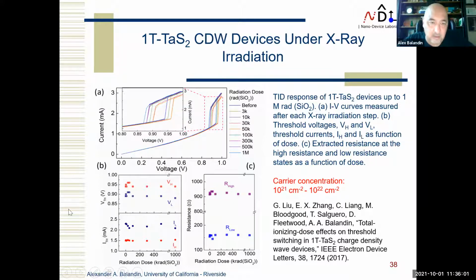So what you look at here is this hysteresis window, which I'm using for my device functionality. We sent the devices to Vanderbilt University, and they applied a very large X-ray dose. And even after this big X-ray dose, the window voltages did not shift. I think it shifted by 2%. So it's very radiation hard.